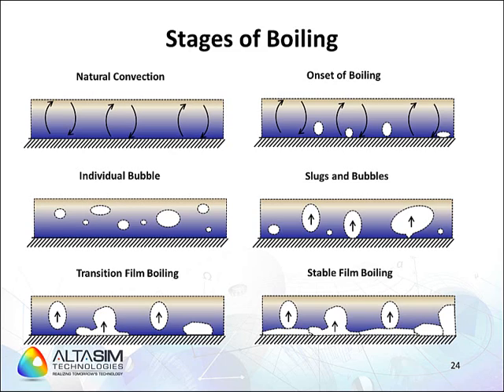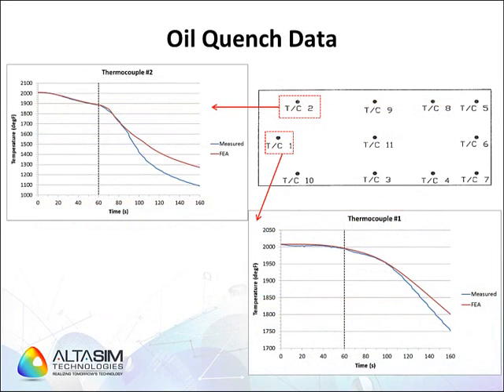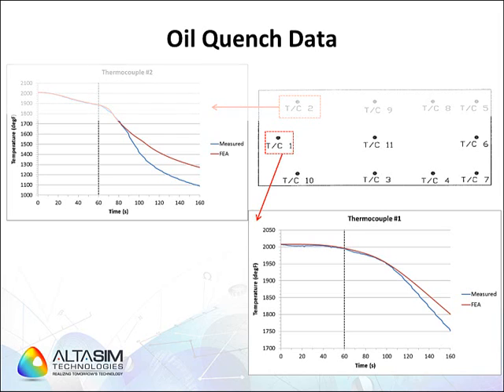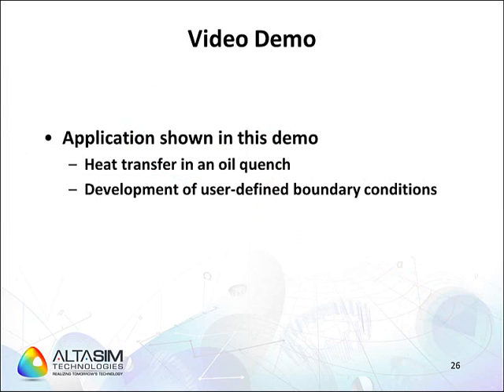As with the air quench, the results from these COMSOL analyses were compared with experimental data for an oil quench experiment. These data show the temperature in degrees F versus time in seconds at two thermocouple locations within the puck. The measured data is shown in blue, and the COMSOL Multiphysics results appear as the red line. These data show that for the first 80 to 100 seconds, the results compare favorably with experimental data. For longer times, these results indicate that we still need to improve the PDEs that we developed to represent the different stages of boiling. If you're interested in a demonstration of how to set up this problem, please review our videos for the setup of the oil quench problem.